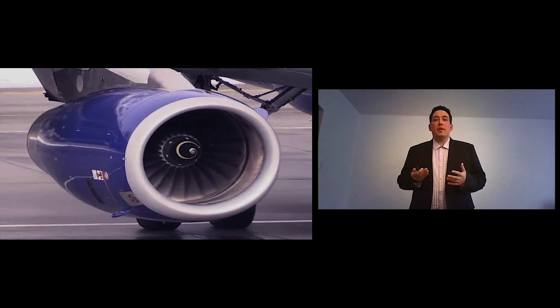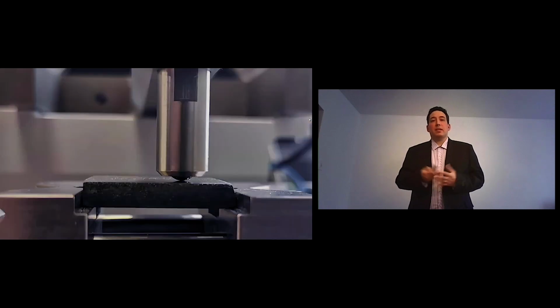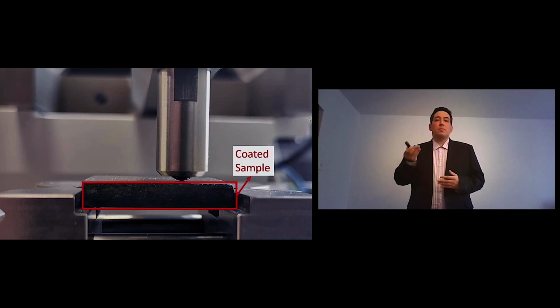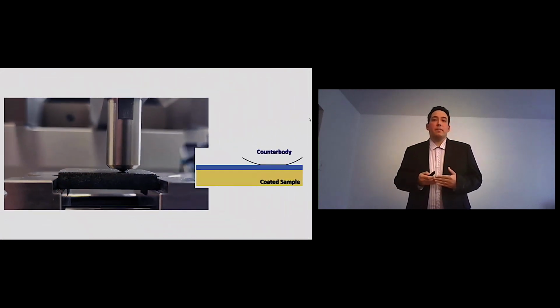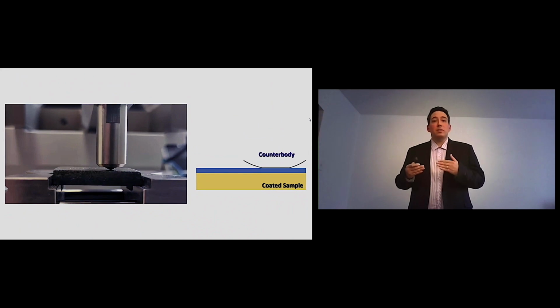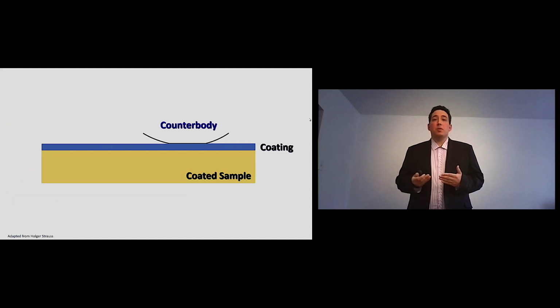We do that by using a tribometer, just like the one you see in the image. What you see here in the bottom part is our coated sample and the counterface on top. So if we were to draw schematics for that, this is what you'd see. The coated sample, the coating that you cannot see right now in the image because it's too thin, and the counterbody or counterface.